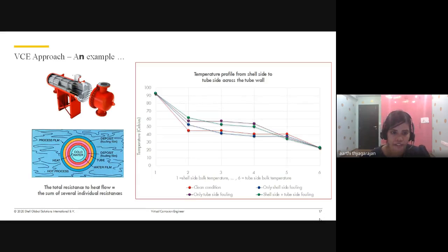So in VCE, we reviewed the process data for these key parameters at Pearl and calculated what is called the cumulative exceedance factor for each exchanger to quantify the extent of deviation from design limits over time. For example, whether it is a closed cooling water type of exchanger or an open recirculating cooling water exchanger type, it will determine the limit of the tube skin temperature and the erosion velocity and the MIC velocity.